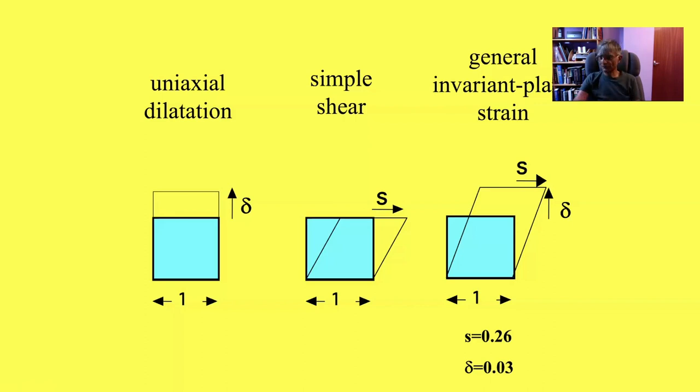So the condition for an invariant line is satisfied, but the shape deformation by itself indicates that the homogeneous strain which carries austenite into martensite is an invariant plane strain. And you'll see that this is actually not the case. This is another one of the puzzles I wanted to go away with: the shape deformation indicates that you can change the austenite into martensite by a shear plus a volume change, leaving a plane completely coherent, whereas I will prove to you later in the next lecture that that is not possible.